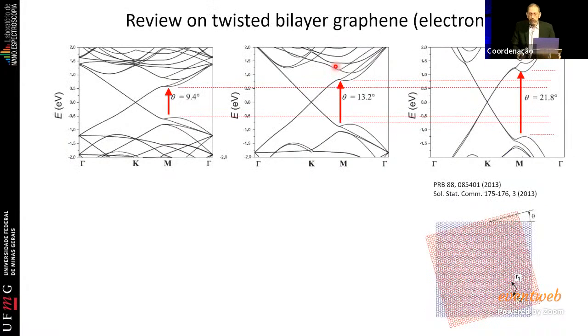And if you go to the electrons, you also have a very interesting and rich phenomenon, okay? If you look into any electronic dispersion relation, every time you have a dispersion relation that has a zero derivative like this, usually you have a high density of electrons at that specific energy. And what you have when you do this twist game, let's say with graphene, is that you can change the spacing between these two levels. Usually the Fermi level is up here. So below this level in energy, you are full of electrons, and above you have empty states. So you can excite one electron from here to here with light or other excitation.